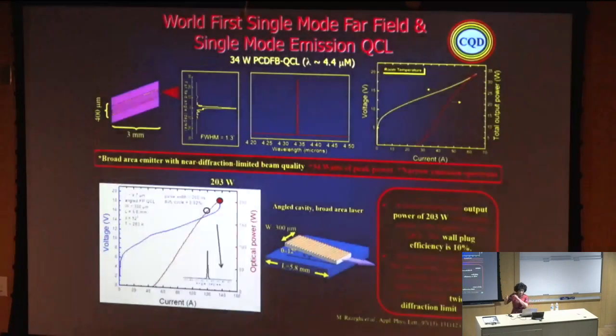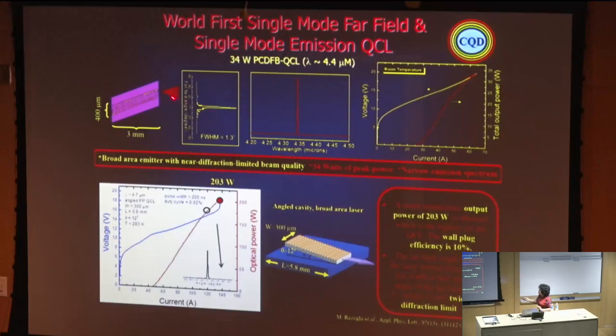So only look here. By using the DFB photonic crystal, that is the structure, with only a 3 millimeter cavity length and only 400 micron width, single mode emitting, the far field is diffraction limited. Single mode emitting output power is 34 watts at 4.4 micron.